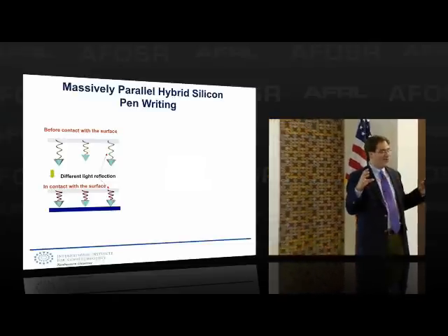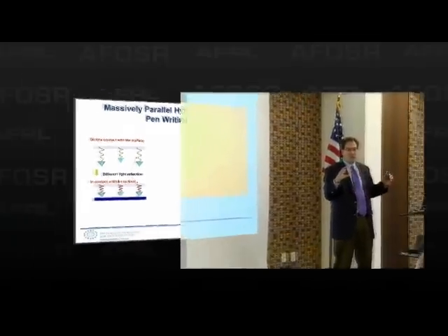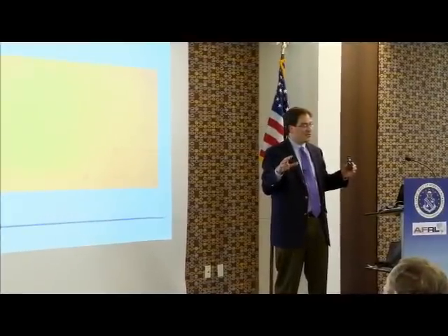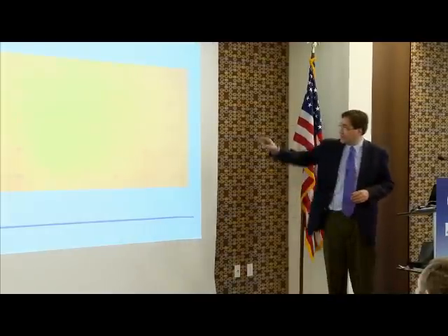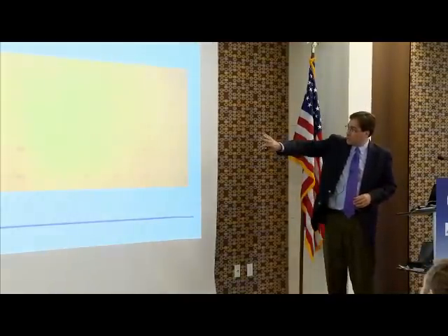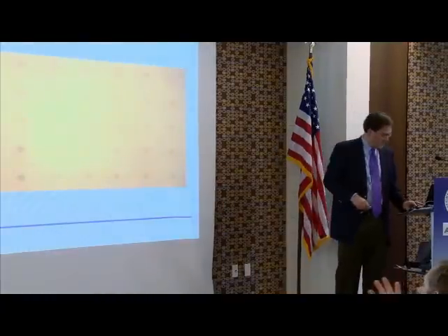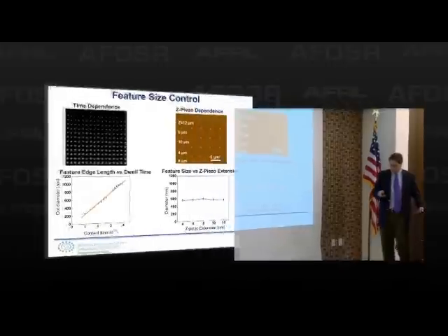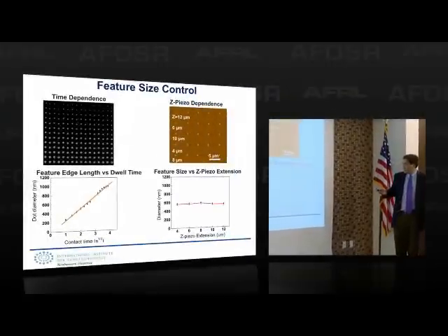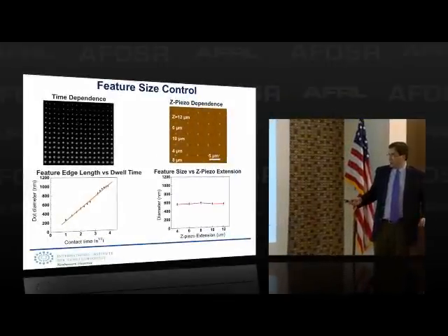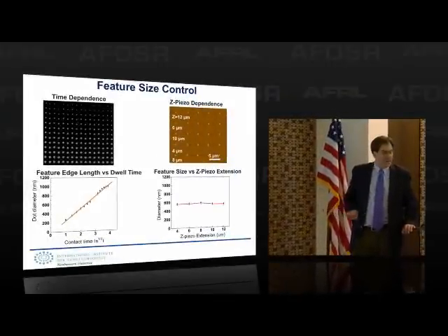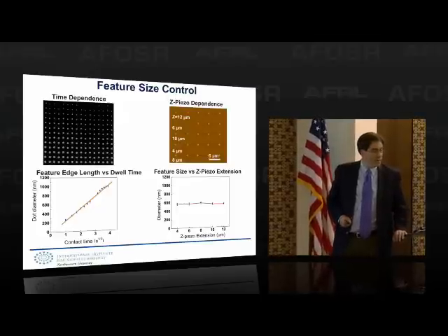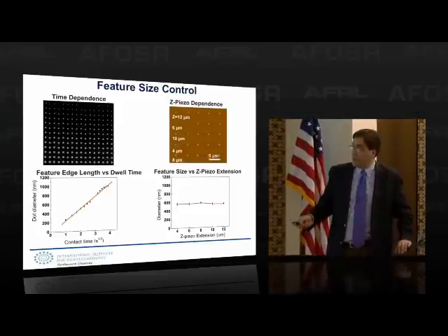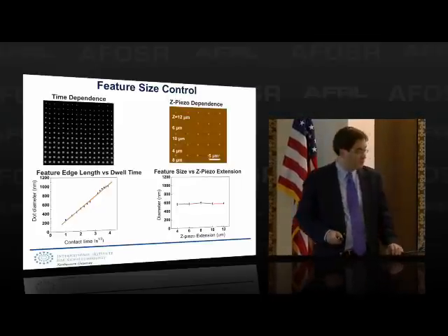So you now literally can use the naked eye to follow when these are making contact with the surface and rapidly align them just by inspection. And when you do that, you can see as the tips make contact, if only one side of the array was in contact, you'd see it deforming, whereas the other would not, and vice versa. You start characterizing this. This is more like a DiP-Pen type of experiment. Feature size is independent of contact force, right? Because the molecules are going to flow. But we can control feature size by dwell time.